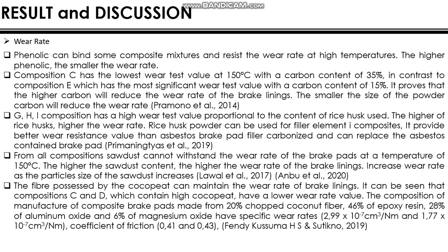GHI composition has a high wear rate value proportional to the content of rice husk used. The higher the rice husk, the higher the wear rate. Rice husk powder can be used as a filler element in the composite. From the compositions, sawdust cannot withstand the wear rate of the brake pad at a temperature of 150 degrees Celsius. The higher the sawdust content, the higher the wear rate of the brake lining. The fiber possessed by the cocopeat can maintain the wear rate of the brake lining. It can be seen that compositions C and D, which contain high cocopeat, have a lower wear rate value.